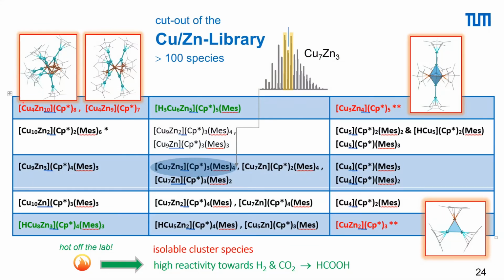Some of them, the red ones, we could isolate and characterize classically by single crystal techniques combined with theoretical modeling. Some are still elusive. And as I said before, there are species which you cannot isolate, but these are the interesting ones. The ones you can isolate are typically less reactive. The ones you cannot so easily isolate probably do an interesting job.